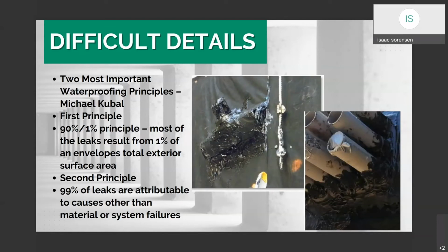If we have a blindside waterproofing application that's literally unreachable, and we introduce a detail that's less than resilient, we're going to see leaking, and the waterproofing installation is then compromised and useless. And costly measures are going to have to be addressed, such as injection of many different kinds to get either into the substrate with a methacrylate, or some kind of polymerized grout onto the positive side to actually just cover up the void that's introducing the water.